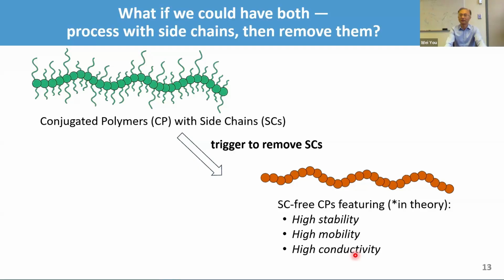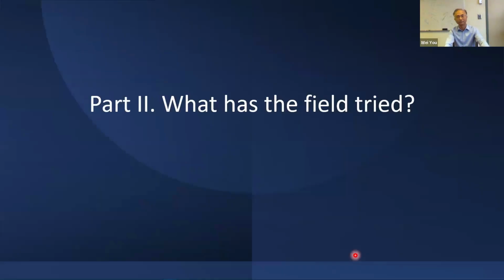That would be ideal because when that happens, you have 100% conjugated backbone in the polymer film, which should give you very high stability because the Tg is high. It should give you high mobility because you have all the pi-stacking you want. In theory, it will also give you high conductivity, because once you dope them, you have a higher charge carrier density, plus a high mobility, and so a high conductivity. But of course, that is in theory, right? So to make that happen is not that straightforward.